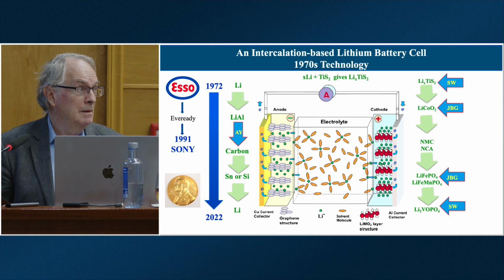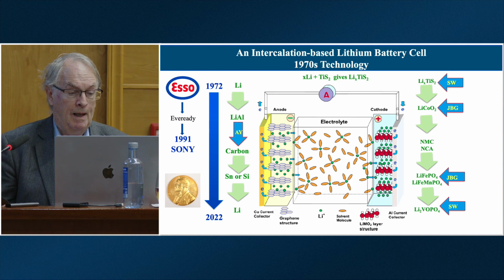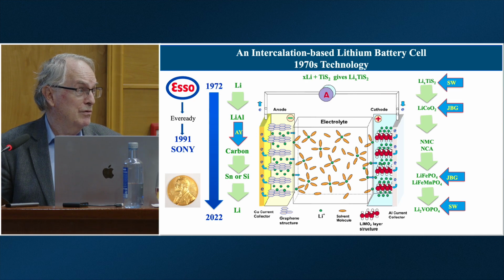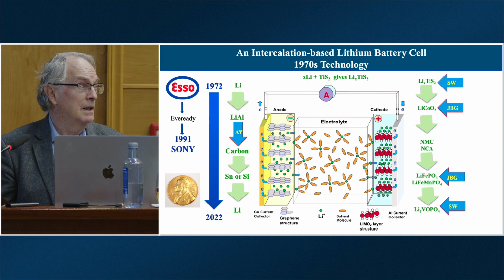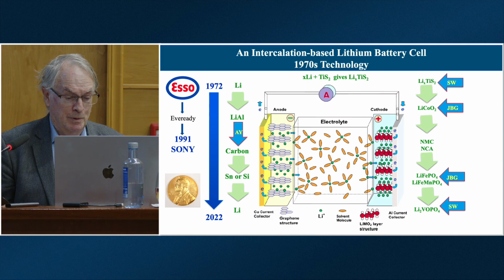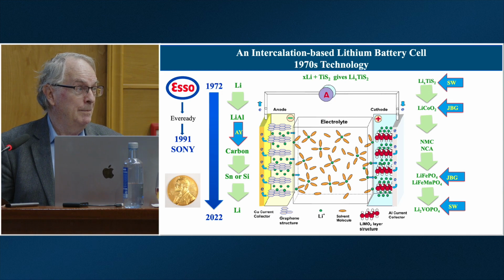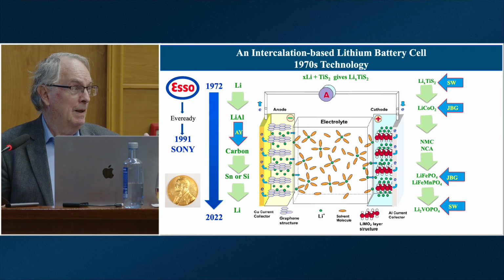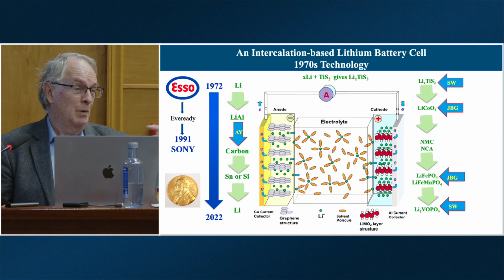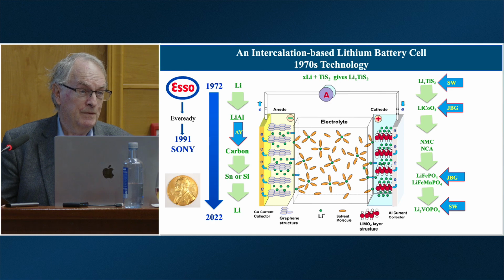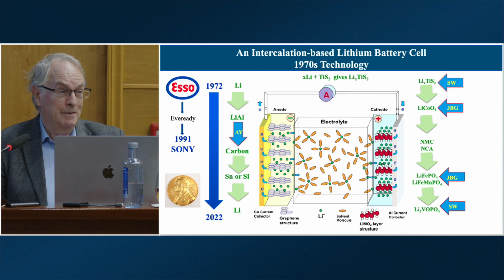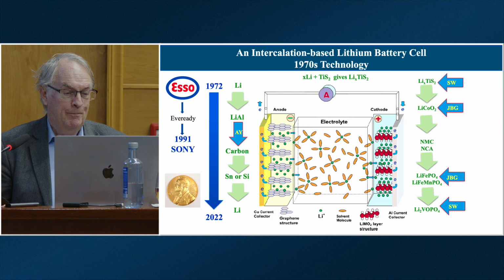So they work very well, but cobalt and nickel are expensive, so you'd like to go to lower cost materials. And John Goodenough again found that these lithium iron phosphates, which are naturally occurring minerals, you move the lithium in and out of those as well. As you'll see in a moment, the energy density of those are very poor. So what we've been looking at recently is, can we increase the energy density by putting 2 lithium ions into a structure, or we could put 1 magnesium or 1 calcium. So we've been working on vanadium phosphates. Vanadium can go from vanadium 5 to vanadium 4 to vanadium 3 with no problems.